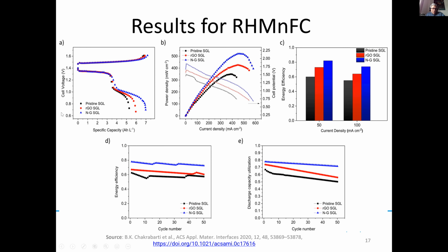So again, first of all, we did the capacity studies for the hydrogen manganese system, and we found that more capacity can be retained when we have a nitrogen doped carbon paper by means of electrophoresis. And then similarly for power density studies, just like the hydrogen vanadium system, we are getting a much higher power density.